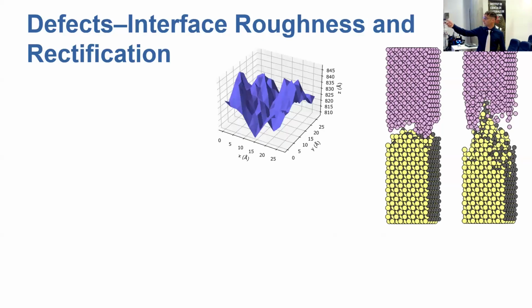Then we moved forward and we studied how interface roughness affects the thermal boundary resistance of the junction. Here you can see a snippet of the interface of the junction with interface roughness. I also applied a minor vertical displacement to germanium atoms in order to help you better visualize the rough interface.